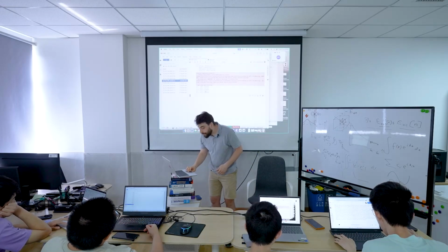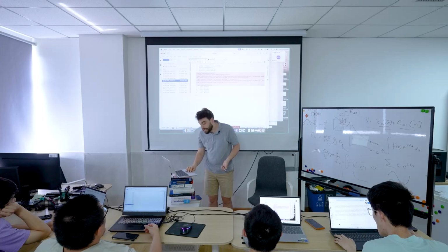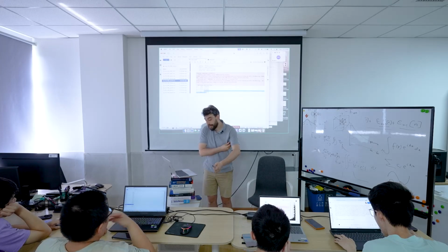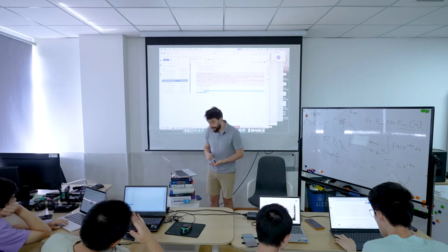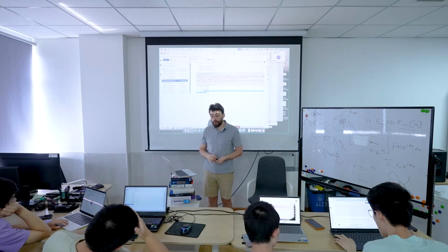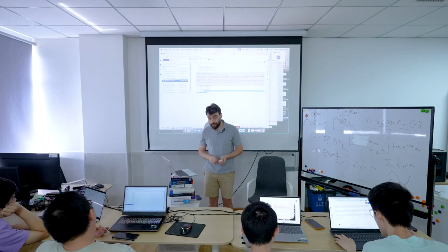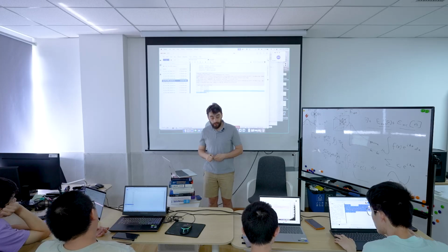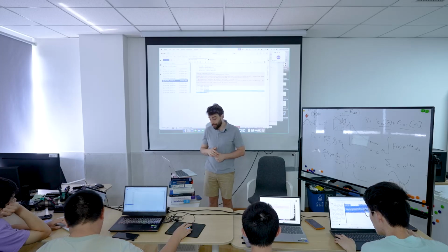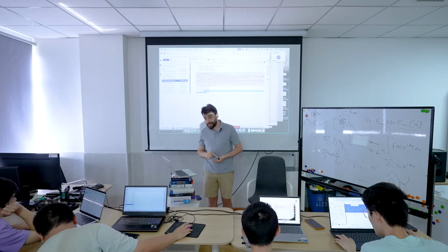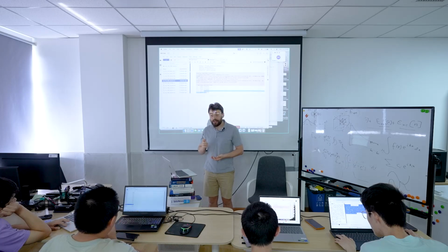Right, so how's it looking? Well, we can see that the difference between 4 by 4 by 4 and 5 by 5 by 5 is about 0.1 eV. Okay, so it's not converged with respect to the arbitrary tolerance that we set, 10 to the minus 2. I expect 6 by 6 by 6 or 7 by 7 by 7.